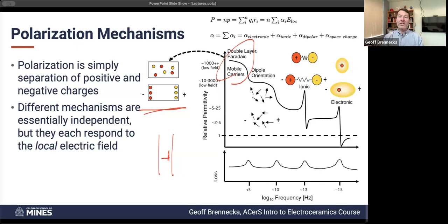The problem is the energy associated with those reactions and the time associated with those reactions means that these are happening at very low frequencies compared to the rest of the plot here. And so depending on all of the factors associated with that, so the kinetics of what's moving, whether or not there are reactions happening, these kinds of contributions are happening at very, very low frequencies. So it might be millihertz, it might be hertz. You're going to be very lucky if you can find a battery that can respond faster than 1 second for large amounts of charge. And so it's the kinetics of those reactions and then all of the other challenges associated with that. So the fact that you're doing chemical reactions, there's strain involved and there's other chemical barriers.